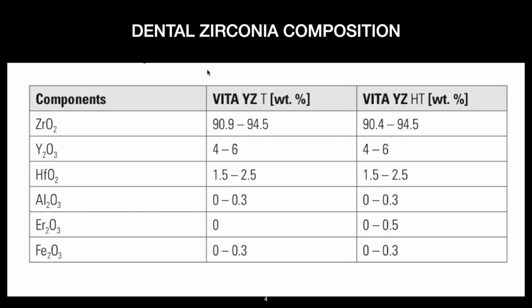So you have dental zirconia compositions. These happen to be some of the VITA material. This is the VITA YZT and the HT, which I don't believe very many people use anymore. These are type 3, 3Y zirconia, which are very strong. But you see all these figures are all over the place, and it's hard to pin down what they actually used. Every manufacturer is that way. But basically, they have almost identical compositions, except the erbium content in the erbium oxide on the VITA HT material. Besides that, everything looks the same.